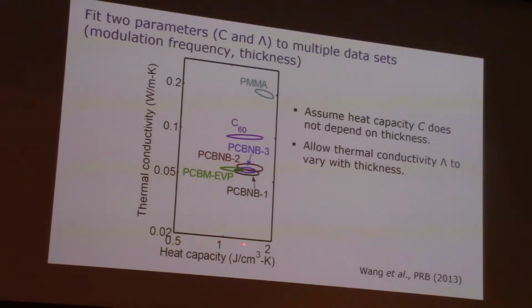So if I plot the heat capacity of the layer, which we measure, and the thermal conductivity of a layer on the same plot, these circles are confidence intervals. We have two parameters, and it turns out they're coupled in complicated ways, so think of it as a two-dimensional error bar. The best fit to the data is the middle of that error bar, and these circles give you something like 95% confidence that the thermal conductivity and heat capacity are inside that circle. This turns out just to be random errors. It doesn't include systematic errors. If you're a measurement geek, you worry about all these things all the time. But okay, it gives you a good idea of what's going on.